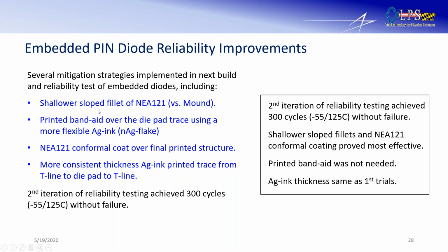So what we did, we looked at it. We wanted to print a shallower slope to get rid of that abrupt transition. We tried printing a Band-Aid ink over top of where the crack would occur. We conformal coated with the same NEA-121, and we tried to print a more consistent ink thickness. So we went back for a second iteration, and we achieved our target, 300 cycles, -55 to 125.